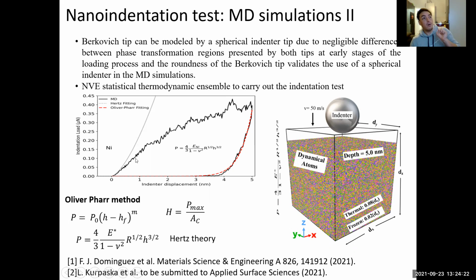Since we're sure that the Hertz theory describes the elastic part, we need to consider many things. Now, the indenter is going deeper and deeper. This is the so-called pop-in. I'm going to show later what the pop-in is, but it's when we start the transition to the plastic region and the dislocations are being nucleated and propagated. Then here we have another pop-in that we are analyzing, and then we reach the maximum indentation depth, and then we do the unloading process.